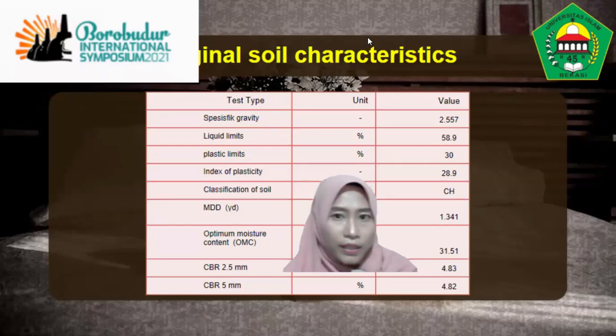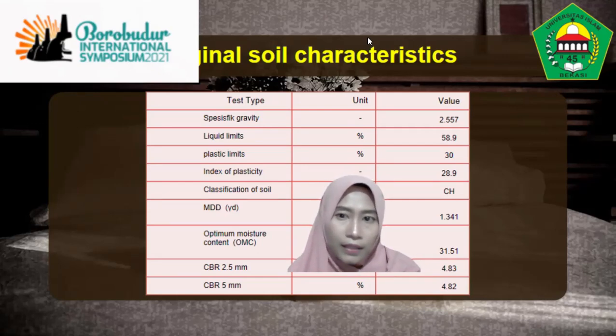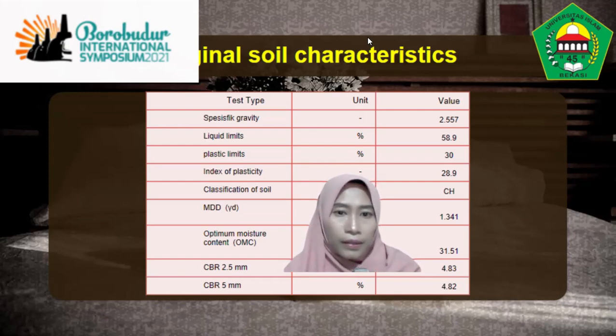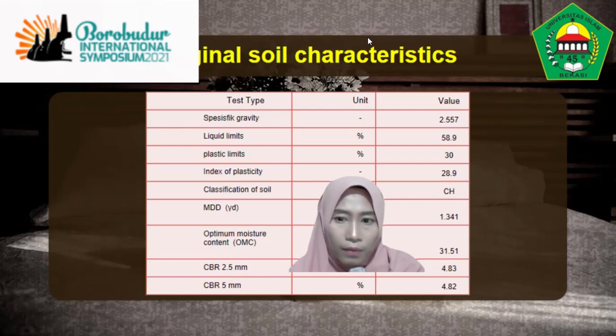This one is the original soil characteristic. The original soil has a specific gravity value, which we can see in this slide. Index of plasticity is 28.9, and CBR at 2.5 millimeter penetration is 4.83%, and CBR at 5 millimeter penetration is 4.82%.